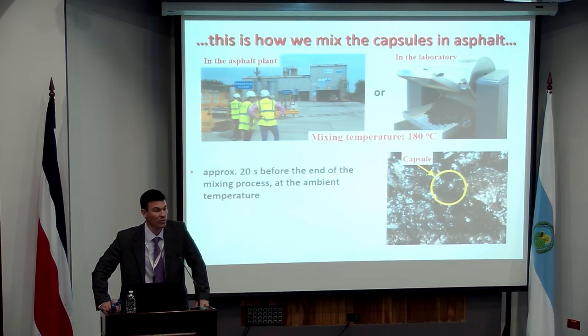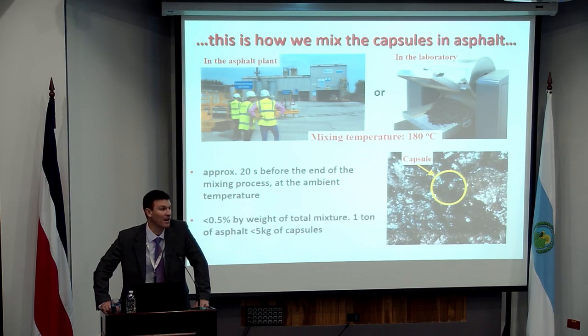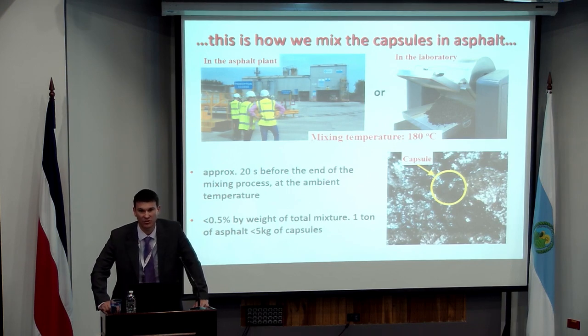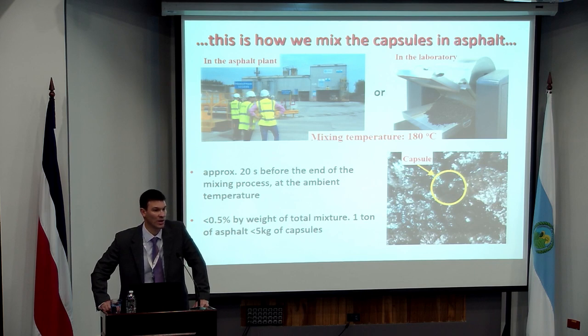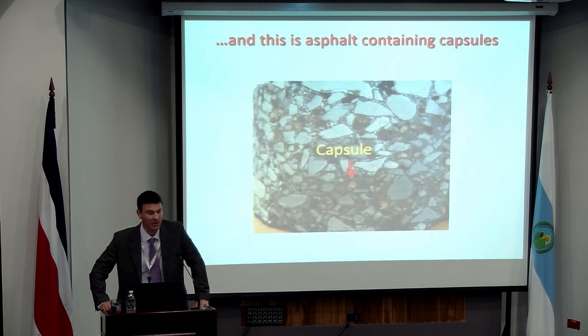And it takes about 20 seconds to actually produce these specimens and about 0.5% by mass of capsules to give you a fairly good distribution inside your material. Relatively cheap, relatively quick process. And that's what they look like when they're inside an asphalt mixture. These are quite big capsules. We've done that deliberately so we could see in this particular trial where the capsules were and how big they were and how robust and how strong they were once they were produced in the asphalt mixture.